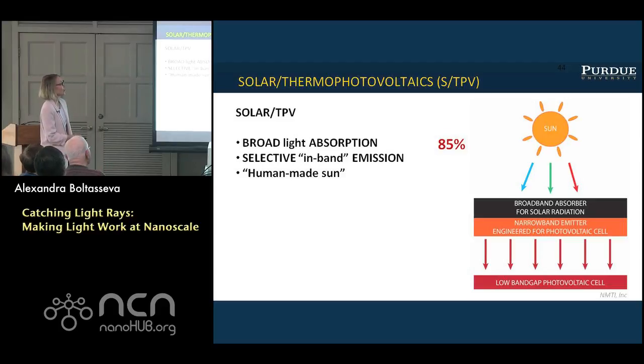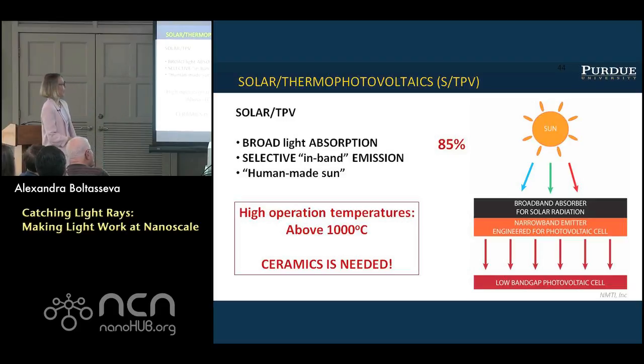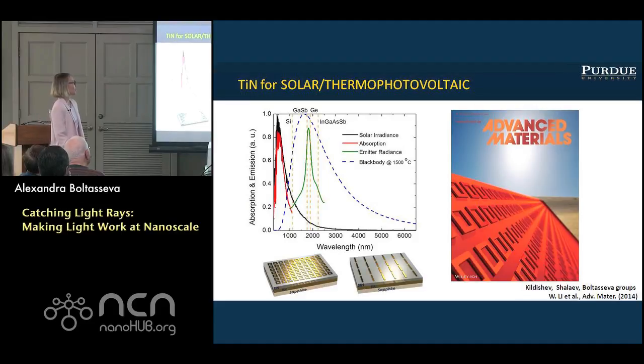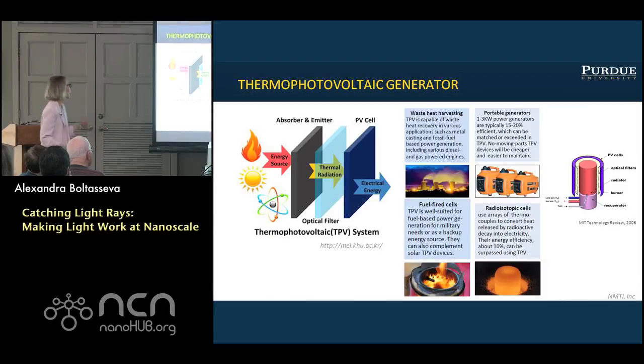So theoretically, you can go up to 85%. Fascinating. And the thing is that since the operational temperatures of your absorber would be around or above 1000 degrees, you need ceramics, and ceramic would be the answer. So we actually demonstrated that using titanium nitride, you can design very efficient emitter and absorber designs.